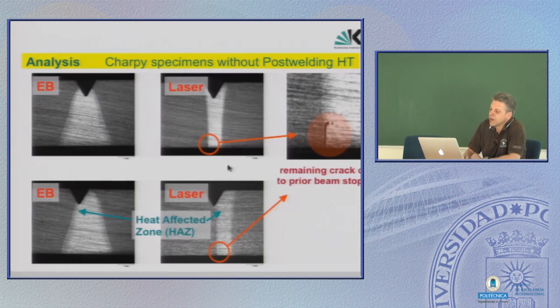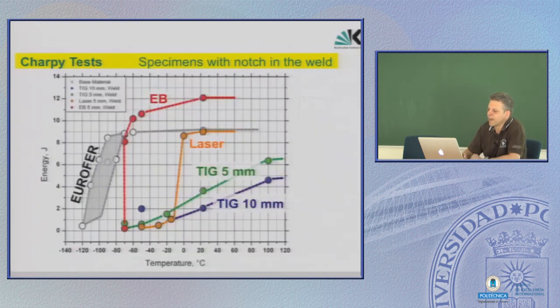These are the welds we have produced. You see here, etched, this is the weld microstructure with the heat affected zone and corner. We performed Charpy specimen tests with notches directly in these welds, but also with notches centered at these heat affected zones. And tests without any further treatment, no post-welding heat treatment as it's called, look like that.